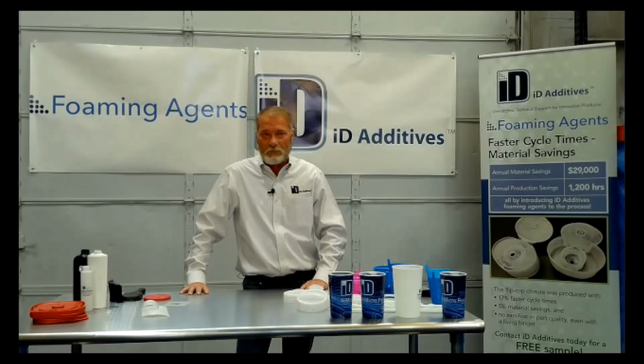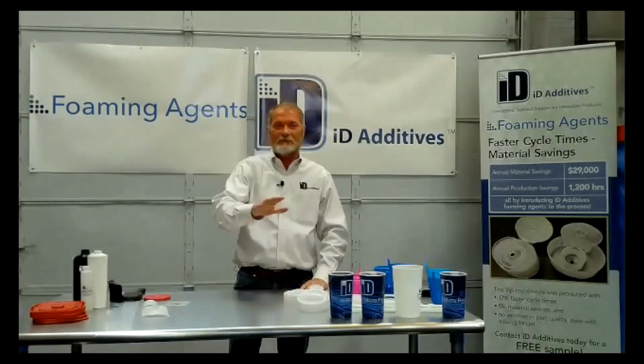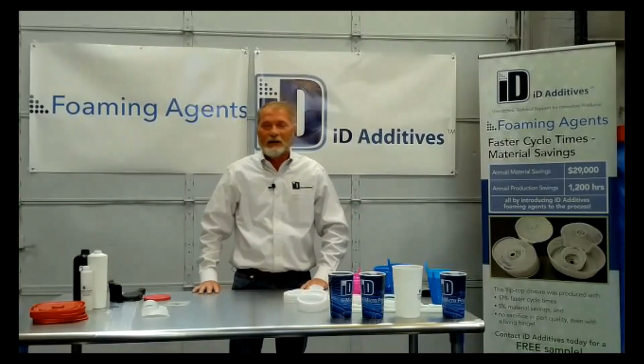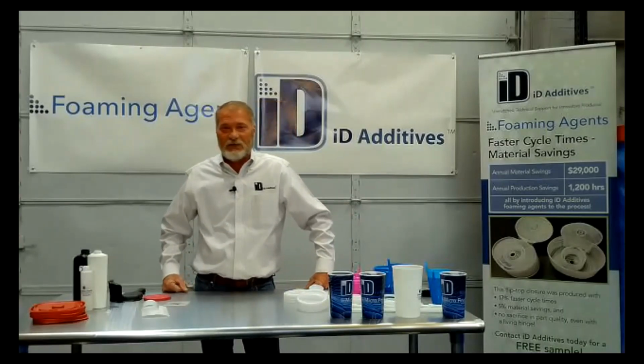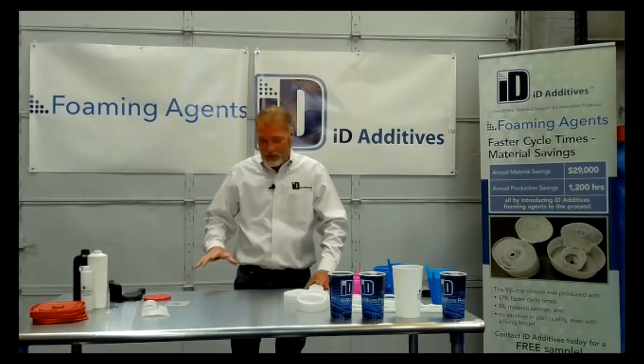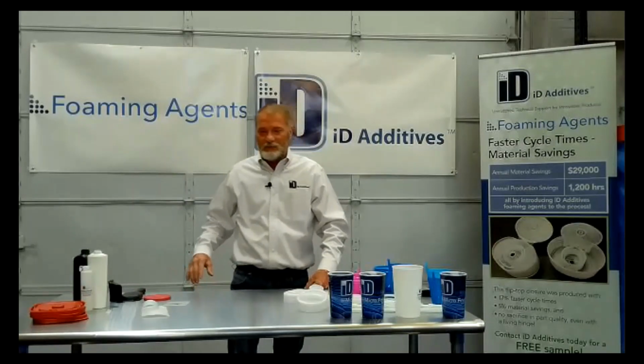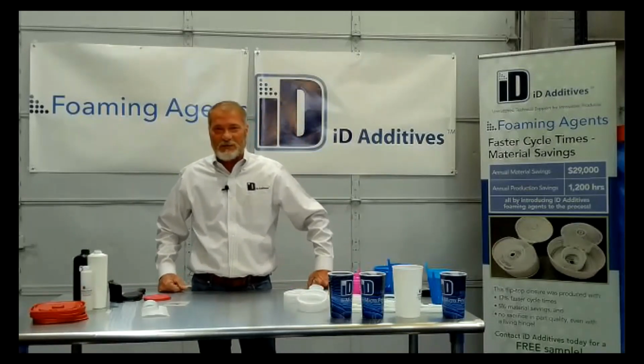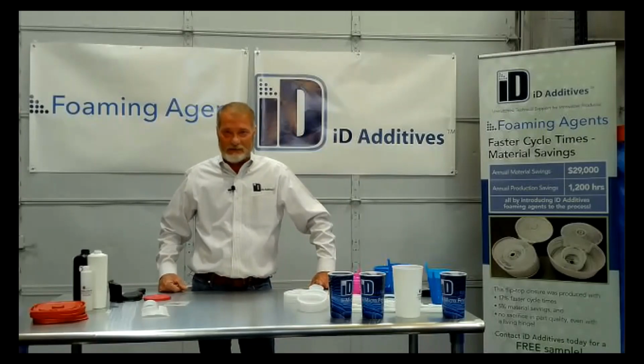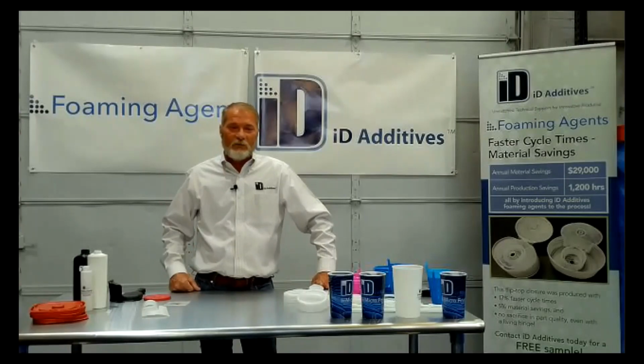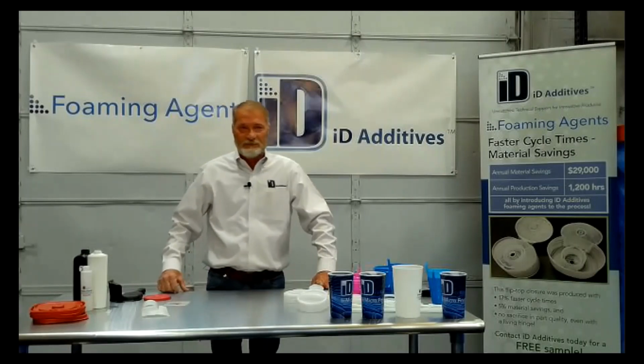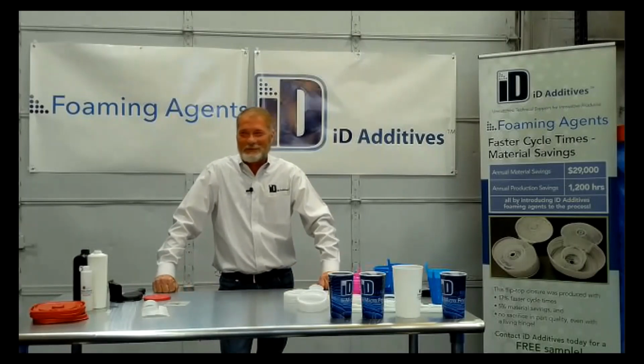This one's going to be a two-parter. I'm going to ask, let me back up, I'm sorry. The shrink. Foaming agent is a filler, right? So it will reduce shrink. There's one application I ran. It was for a part underneath a motorcycle seat, and I fully foamed it. We had to speed it up 15 seconds to get it down to size because it was so big. So foam will reduce shrink. Good. I'm sorry, go ahead. You're fine, man. It's your show.